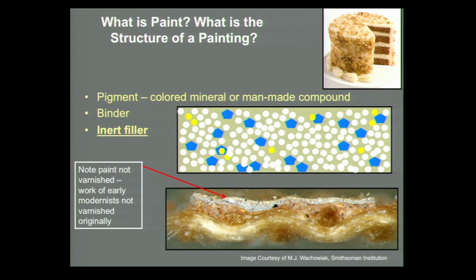Now, when we're studying a painting and we need to take a sample, then what we do is use a small scalpel, like the type of scalpel you would use for eye surgery, to take a tiny flake of paint. We mount it up in polyester resin and polish it until you can see the paint layers end on. And that's what's shown here, a side-on view of the paint layers or cross-sectional view. So it's just like when you cut into a slice of cake and the layer structure is revealed. And so we see the same thing here.